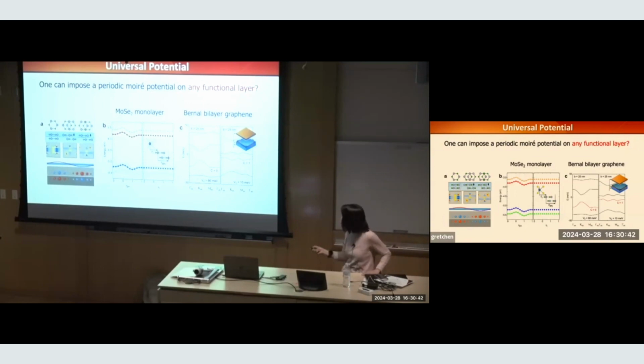So there are a lot of things I can do starting with a modulation potential from a substrate. So I can choose really very different functional layers. And I was talking to Oliver this morning and he said, okay, you have a ferroelectric material now, put a magnetic layer on top. Do you have a multiferroic material? Not so quick, because you have to make sure they're actually coupled to each other. The electrical polarization may not be coupled to the magnetic polarization. You need to think about that carefully. How do you make that happen?